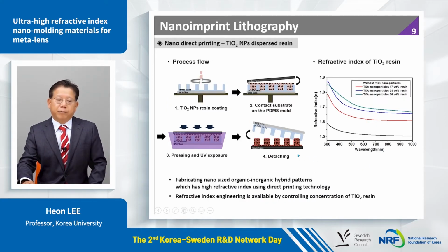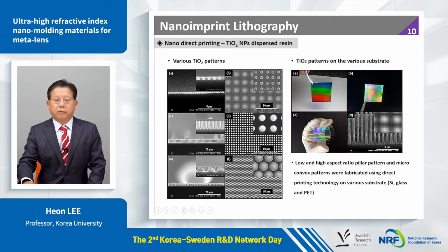And another thing about nanoimprint lithography is that we can do some material science. By mixing high refractive index materials such as titanium oxide nanoparticles into the imprint resin, we can adjust the refractive index as we want. And at the same time, we can make some nice nanoscale patterns, nano to micro scale. This is a nano dot array. This is a high aspect ratio pattern. This is a micron size microlens array pattern. We can choose a silicon wafer as a substrate, or flexible polymer film, or glass substrate. So, using nanoimprint lithography, we can fabricate nanoscale patterns of any material on any substrate.